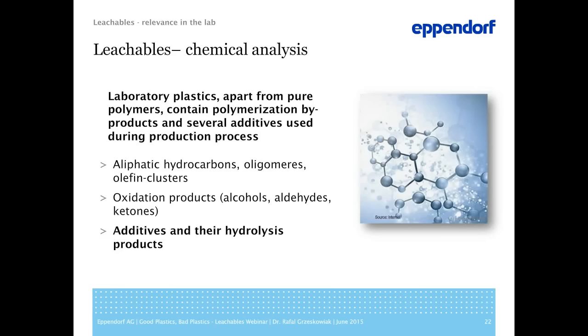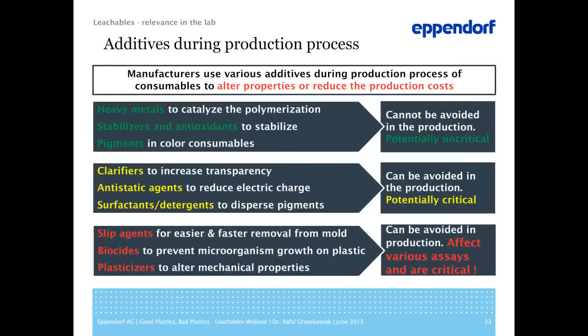Contrary to common belief, it is made not only of pure polymer. Apart from polymer molecules, laboratory plastic contains various polymerization byproducts like aliphatic hydrocarbons, oligomers, olefin clusters, and oxidation products, for example alcohols, aldehydes, and ketones. But also, more interestingly, it contains various chemicals added during the production process, additives, and their hydrolysis products. This group is largely responsible for most of the negative effects leachables have on various assay systems. So let's have a closer look at the additives used during the production process.